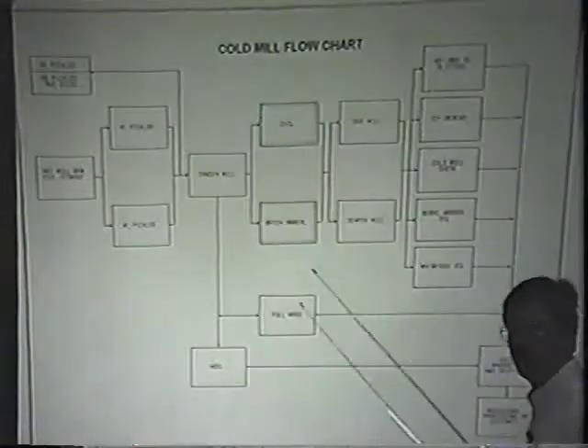We triple the strength. While we're tripling the strength, we're also removing its ability to stretch, or removing its ductility. So it's a real hard piece of steel, but it's basically useless. If you bend it much more than very generous 90-degree bends and roll form, it's going to break. You can't stretch it. You can't put it in a draw die. It's got very few applications. So after we cold reduce it, we have to anneal it, soften it back up.